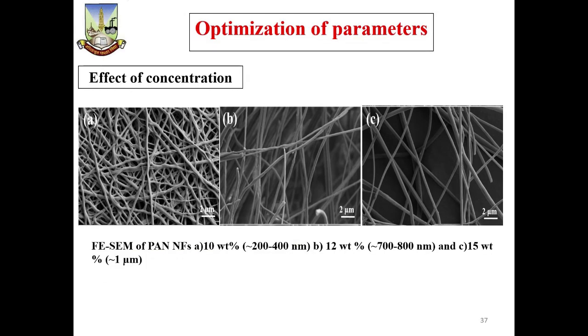When optimizing parameters like concentration of the solution, what will be the structure of the nanofiber? That picture suggests different molecular weight or viscosity. When the concentration is 10 weight percent, the fiber obtained is between 200 to 400 nanometer. If we enhance it to 12 weight percent, it goes to 700 to 800 nanometer, and again if we increase up to 15 weight percent, it gives 1 micrometer.